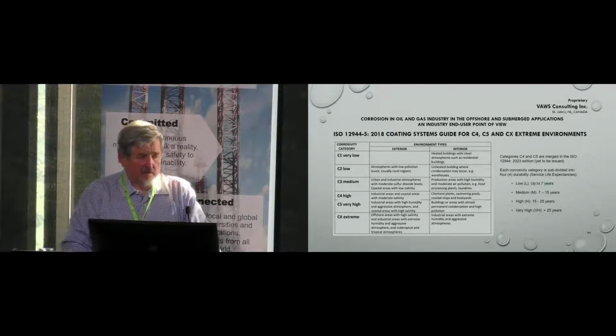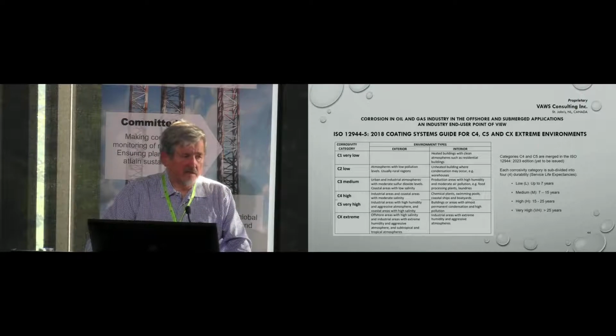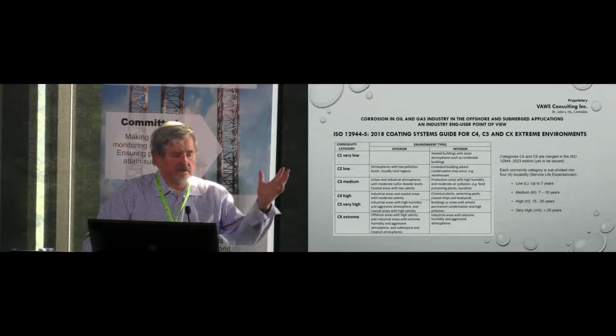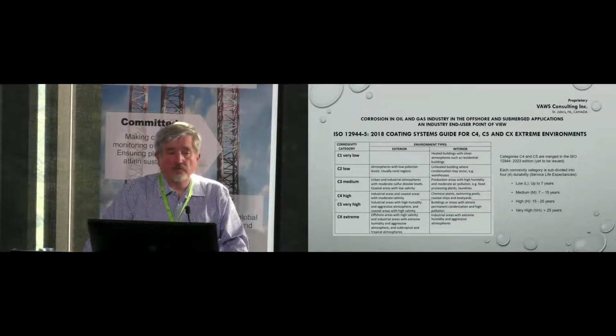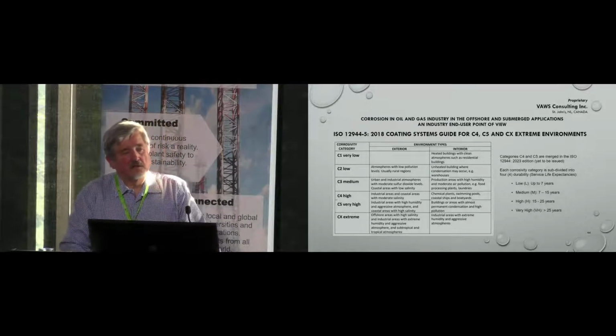They tested the paint according to the NORSOK standard, and it went through with no problem, laboratory testing. But what was delivered to site was completely something different. It wasn't the coating they tested, and it failed miserably. Basically, it failed when it was in transport from the factories which fabricated it to Canada.